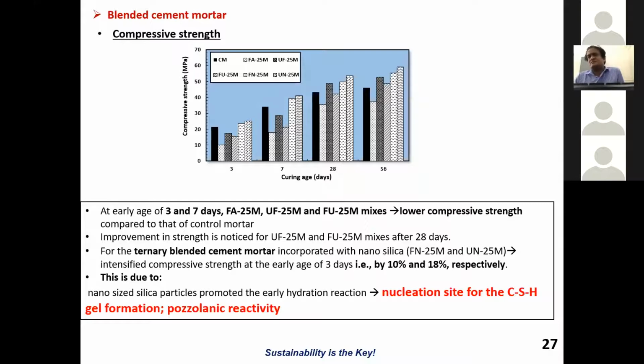Then the compressive strength. At the early ages of 3 and 7 days, as I was telling you, when I go with the fly ash mixes, or fly ash replacement, mostly I get lower compressive strength compared to the control mortar. That is natural. But if you go towards 28 days, the improvement is much better.